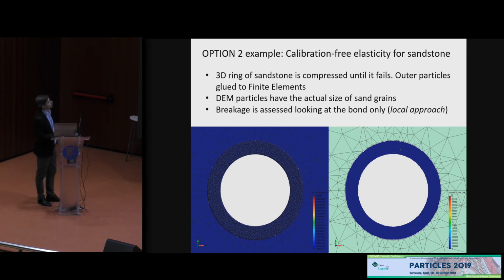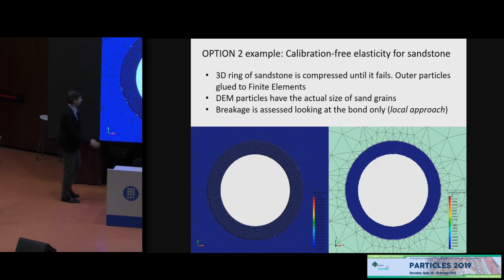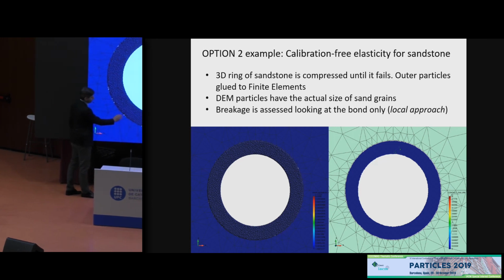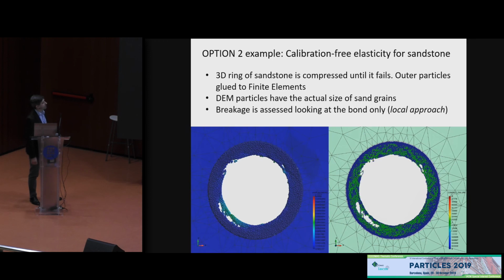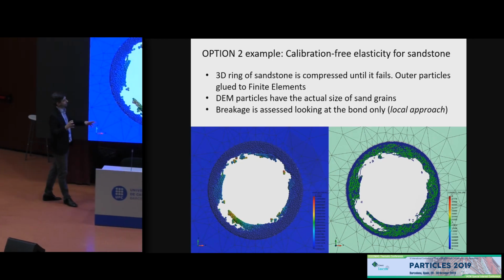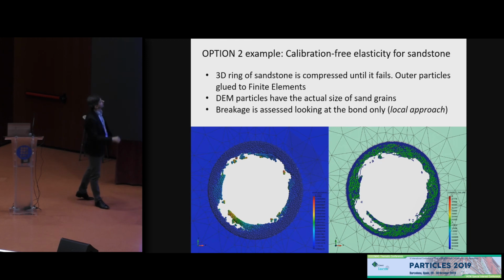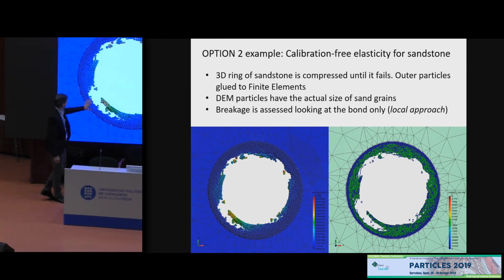This is an example of option 2. This is a ring made of sandstone, which is coupled with an FEM simulation. So these particles are glued here, so they are moving with exactly the same displacement. And we are compressing the whole domain from the finite elements and trying to see how much of this ring is broken and detached from the ring. And breakage is only assessed looking at the bond. Here we are not using the stress tensor for the breakage, but we are using the stress tensor for the elasticity. So elasticity is calibration free, let's say, and we have here these chunks that are leaving the domain, this chunk which is almost leaving the domain, and there you have the bonds that are reaching the limit.